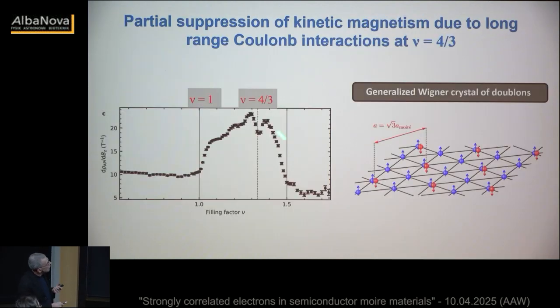So I just want to say that I forgot to point it out, that we have this correlations increase, and then there's a dip at 4/3. We believe that what's happening here is that the doublons form a Wigner crystal. And when they form a Wigner crystal, then basically the magnetic correlations are gone because we no longer have an equivalent doubling system. Okay? It's not perfect. Normally this should go down to unity, but that's due to moire disorder in the system.